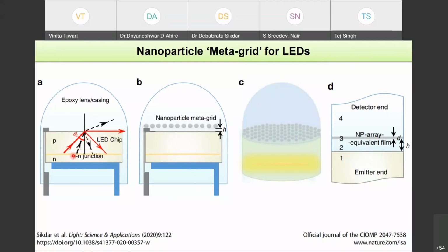Now, if the incident light has a lower angle than the critical angle, then some portion is definitely getting transmitted, which essentially escapes from this casing and comes out to us. But there is a significant amount of reflection happening at the interface for these black cases also. So this loss is called Fresnel loss.